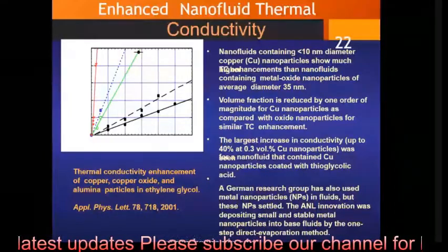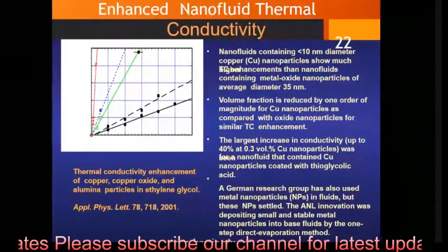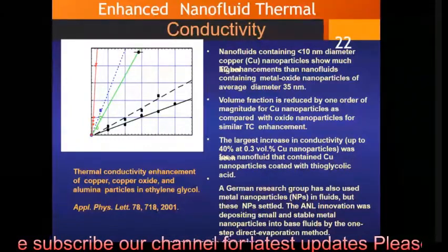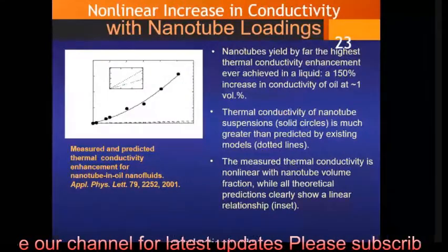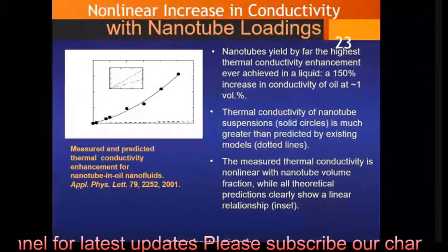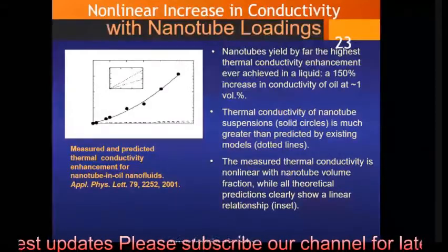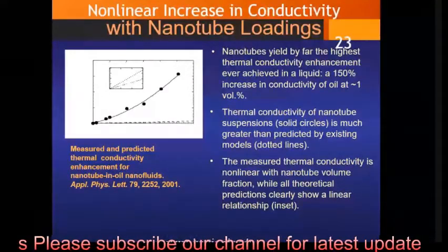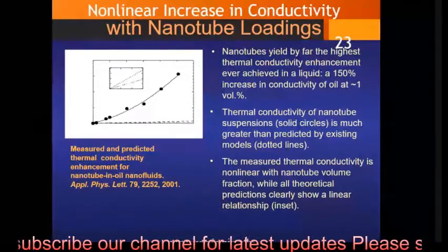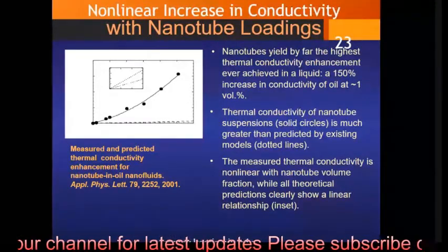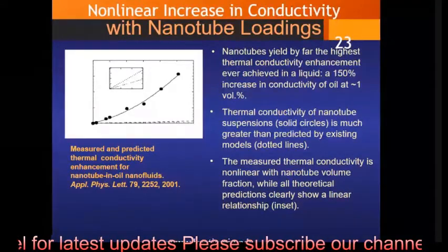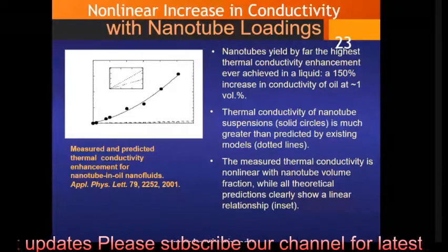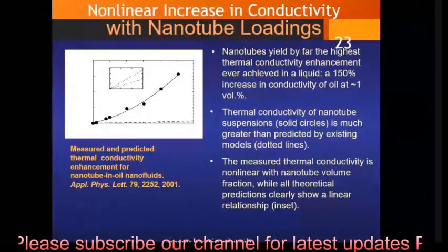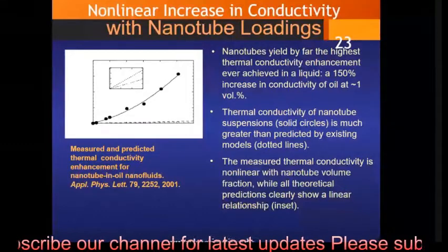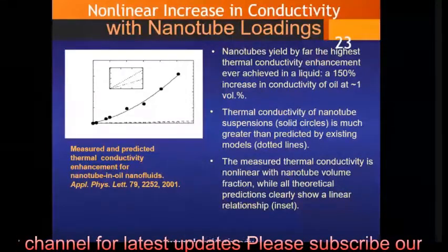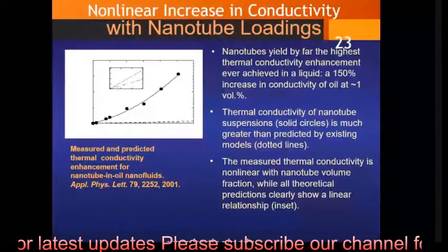That is copper nanoparticles coated with thioglycolic acid. Many researchers are already working on the nonlinear increase in thermal conductivity with nanotube loadings, which is about the suspension of the solid circles with the dotted lines in this diagram. It is very difficult to predict the enhancement of nanotubes in oil nanofluids, because oil has different fluid structures with different concentrations and other fluid parameters, including viscosity. So there will always be some resistance to flow.